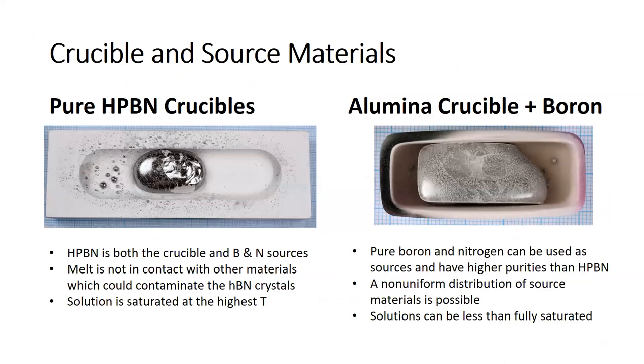And so the first thing we encountered is what to use as a crucible material. First we started out with a hot press boron nitride crucible, the idea being in that case, the flux wouldn't touch anything but the same sort of material. So we're thinking there'd be no contamination by contacting other materials. One drawback to this is the solution's always saturated in contact with the boron nitride. So we've also tried alumina crucibles, and they work just as well. In this case, we can use pure boron as a source.